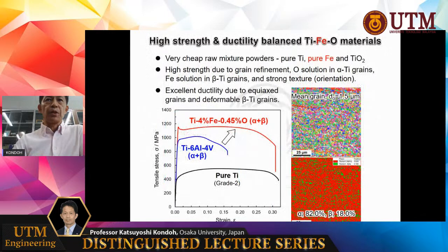Another example is the case of titanium with oxygen and iron, like these ternary alloys. Of course, iron powder is very, very cheap. In that case, we mix titanium powder, iron particles, and titanium dioxide particles. Three kinds of powder are premixed, pressed and sintered, and plastic deformation was applied. And as shown in these stress strain curves, the red line is the titanium, iron, oxygen ternary alloy.